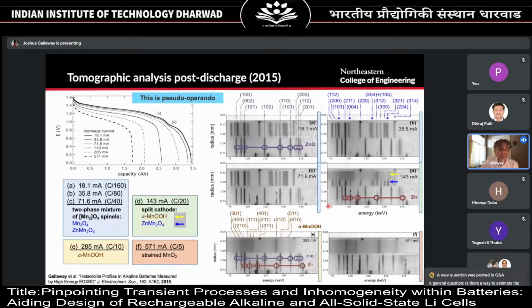So we tested several batteries and did our EDXRD technique on them while we were discharging through that point. And that point was right here. If our data begins with the red and goes to the violet and the black, we see this peak, and then a second shoulder begins to form right there, and then after that, another peak starts to form.